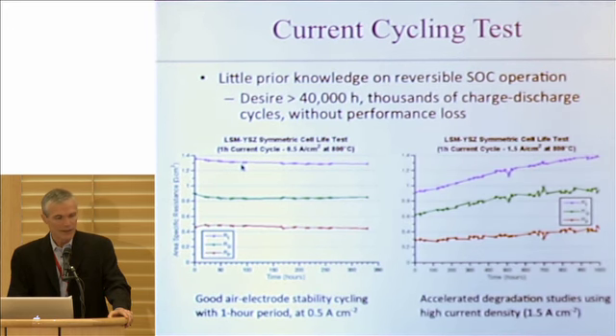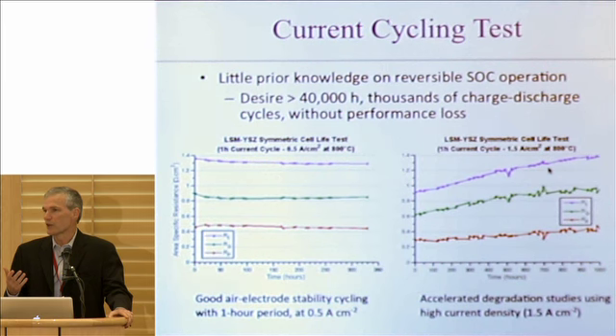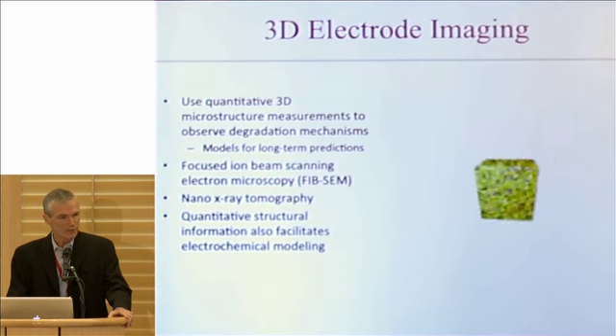Not so good news if we try to go to much higher current density. If we want to run these things at much higher powers, this is now 1.5 amps per square centimeter, and we are seeing degradation. This is actually maybe an opportunity where we can use the higher currents to accelerate degradation and study what are the processes going on. And we are planning very detailed studies of this.